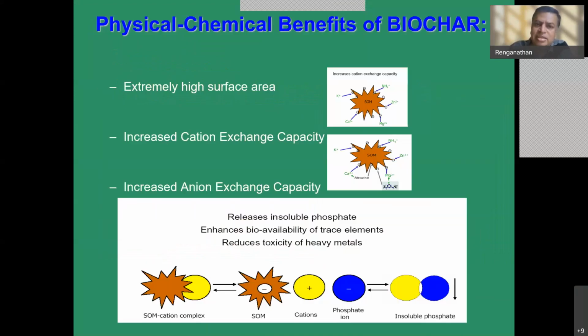And it is an extremely high surface area, which increases the cation exchange capacity. The biochar-amended soils have a cation exchange capacity of close to about 100, and the best of soils have a cation exchange capacity of about 30. So you can see that you can increase the cation capacity by 3 times by adding biochar. It also increases anion exchange capacity.